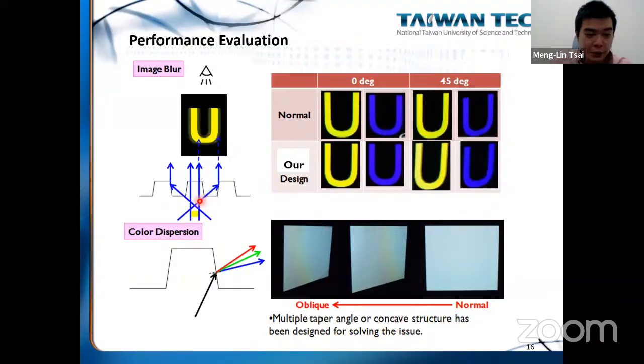But later on we found out that this image blur is actually due to the total internal reflection of the sidewall. And also there's another side effect. Remember we talked about the color dispersion problem. For a single angle trapezoid structure, you can see that different color light tends to diffuse to different angles, right? So after you apply a film on your display, if we come up with a white screen, at certain angles you will see this rainbow color. This is due to the color dispersion problem.